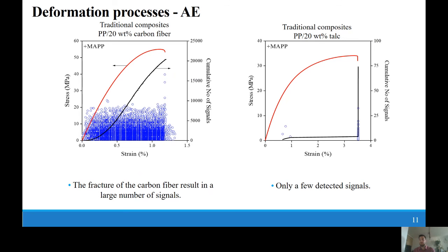given deformation. The shape of the curves and the number of signals can provide information about what was the dominant deformation process. In the case of carbon fiber composite, the process takes place at small deformation. This process is the fracture and the pull out of the fibers. The number of signals is around 20,000.